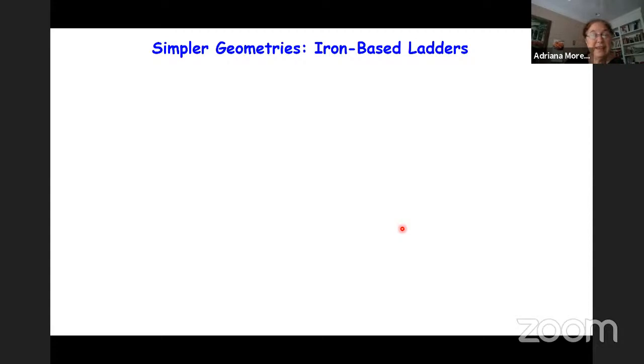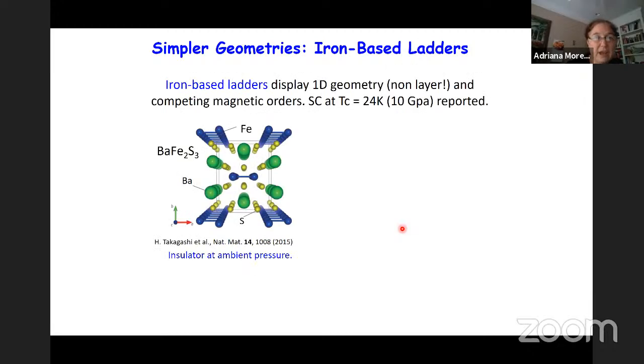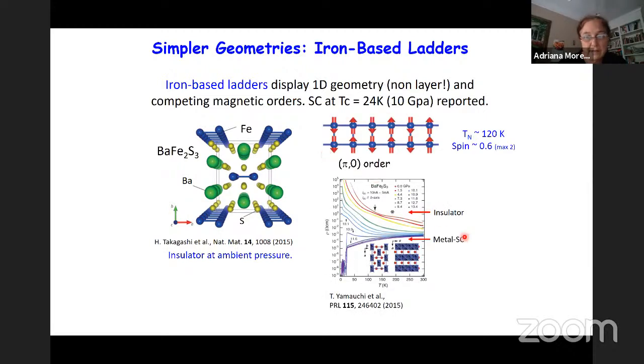So the issue is that nature helps us, because there are iron-based ladders. Barium iron sulfide is a material that actually contains ladders of iron, so it has a 1D geometry. It's an insulator at ambient pressure, but it becomes superconductor with a TC of 24 Kelvin at 10 gigapascals. So here you can see how it's an insulator. This is the resistivity, but under pressure, the resistivity goes down, and eventually we end up with a superconductor.